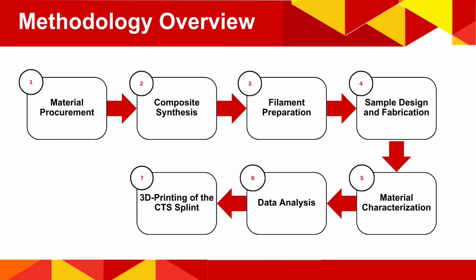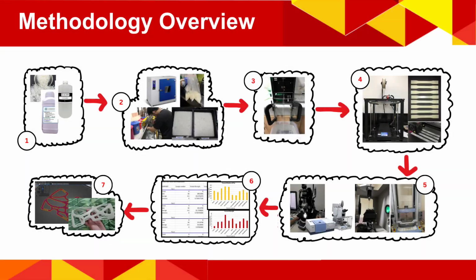To develop and evaluate our composite material, we follow the structured experimental process. Material procurement, sourcing PLA, OMMT nanoclay, and glycerol. Composite synthesis, melt intercalation using a twin screw extruder. Filament preparation, pelletizing, drying, and extruding filaments. Sample design and fabrication, using Onshape and FDM 3D printing. Material characterization, testing mechanical, thermal, and surface properties. Data analysis, statistical evaluation via two-way ANOVA and HSD. 3D printing of CTS splint, fabrication of the final optimized wrist splint. Each step ensures that our material is suitable for orthotic applications, balancing strength, flexibility, and durability.